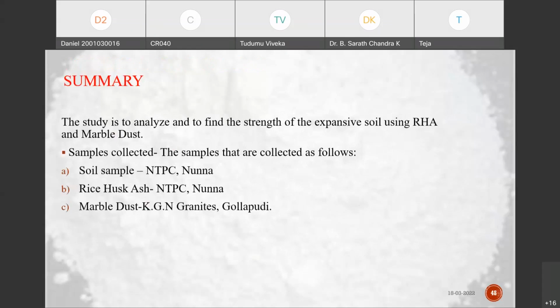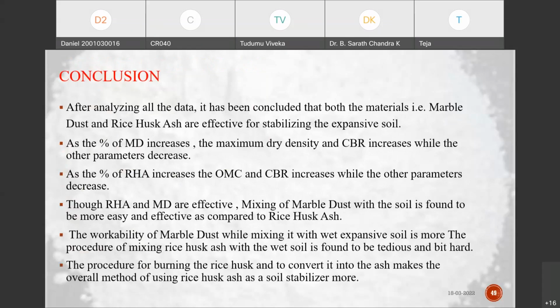The summary is that samples are collected and tested in the lab, and it is concluded, after analyzing all the data, that marble dust and rice husk ash are very much effective for stabilizing the expansive soil. As the percentage of marble dust increases, the maximum dry density and CBR increase, while the other parameters decrease. And if we see RHA, as the percentage of RHA increases, the optimum moisture content and CBR increase, while the other parameters decrease.